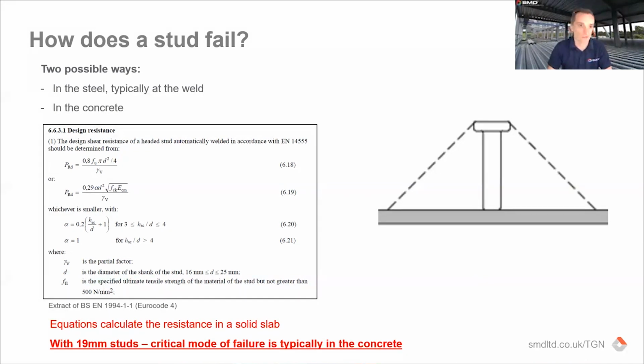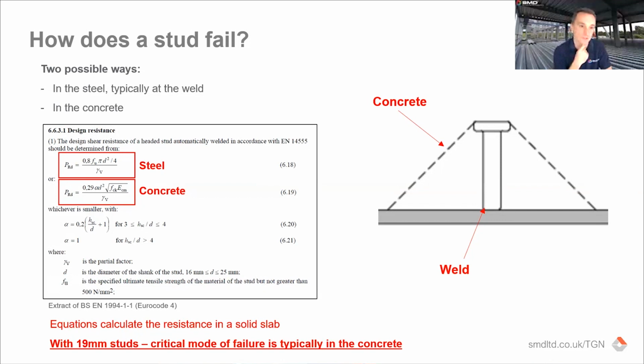So first of all, you need to determine the resistance of the shear stud in a solid slab, and we do that by two equations from the code. Those equations are essentially saying, this top equation here is all related to the steel aspect, so the strength of the shear stud, the diameter of the stud. So it's more talking about, have we got a failure in the stud connection itself? The second is in the concrete, so it's related to the concrete compressive strength and to do with essentially the cone of failure that you would get.